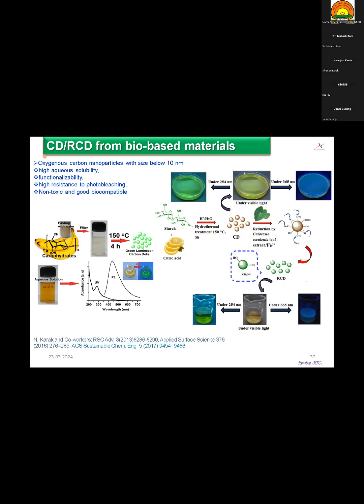These carbon dots, which are obtained from carbohydrate just by thermal heating, even in a glass bottle at about 150 degrees centigrade for 4 to 5 hours, or in an autoclave, will produce highly luminous photoluminescent carbon dots, which can be further reduced, just like graphene oxide, to get much more effective photoluminescent reduced carbon dots.